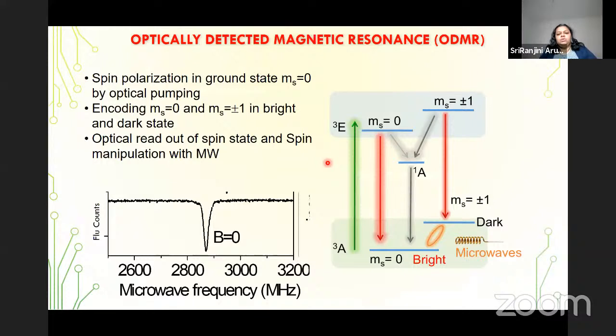Going into some of the spectroscopic properties, which are a signature of this nitrogen vacancy center, one of them is optically detected magnetic resonance. You all must know about magnetic resonance. Here, we do magnetic resonance by using optics. So this is ODMR, optically detected magnetic resonance. Considering the simple Jablonski diagram of the NV center, it has a triplet state, a triplet A to triplet E transition, ground state to the first excited state.